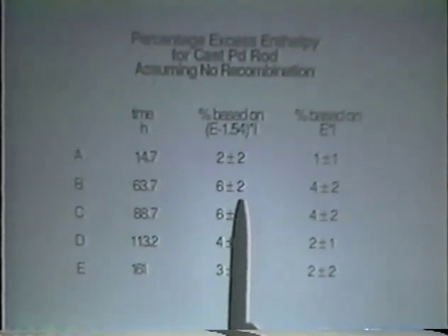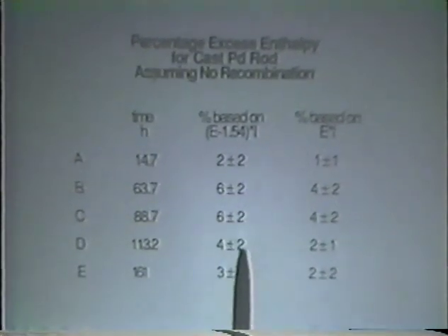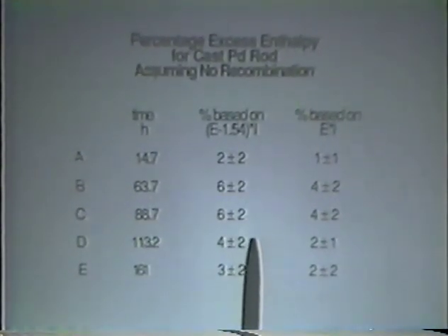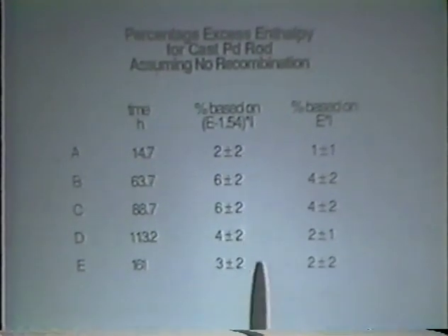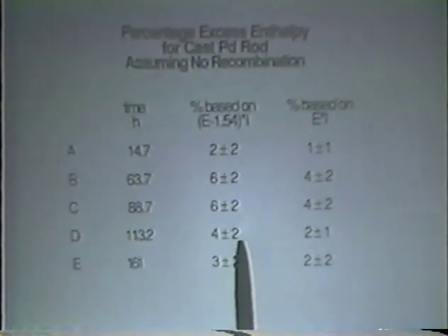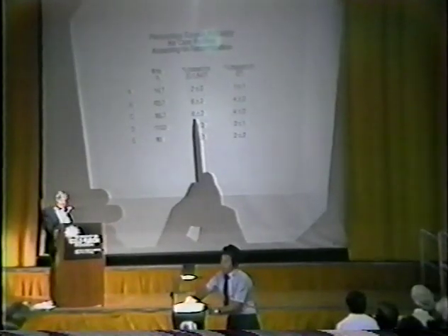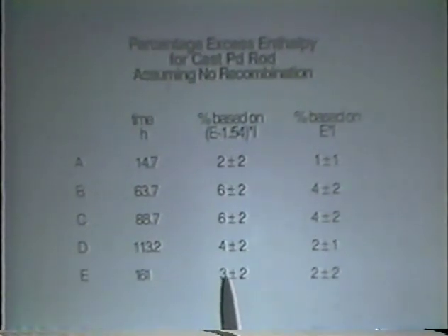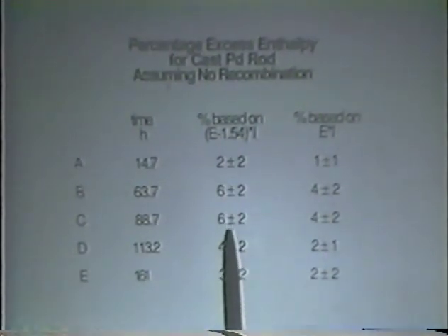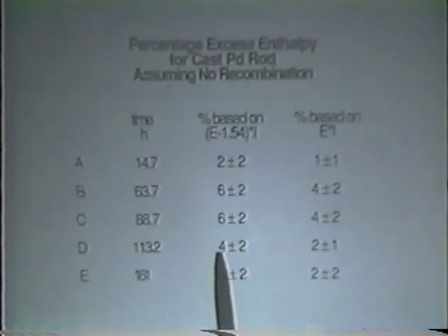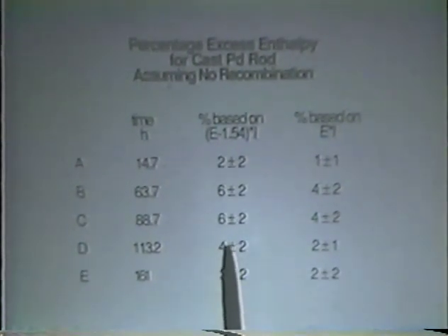This is given by standard systematic errors in both the measurement of the thermocouple, in our estimates as to other variables in the cell. These numbers could certainly be accounted for by some small amount of recombination. These are if they were 0, that would be the coolest the cells could ever be given that input power and all the gases escaping. It's very reasonable to assume that not all of the gases escape given that we have platinum and palladium around.